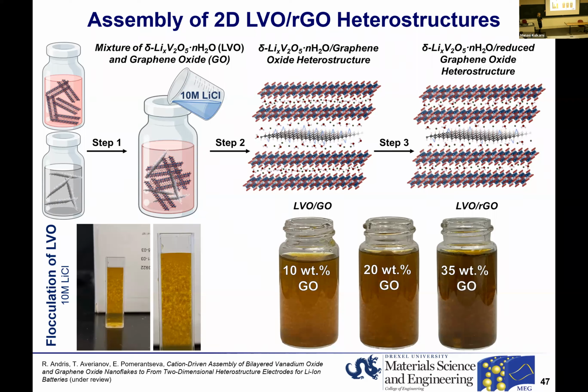So again, by introducing this positive charge from lithium ions, it results in agglomeration of the bilayered vanadium oxide nanoflakes, and that leads to the formation of these agglomerates, and then they can be filtered and form a freestanding film. And this is how these suspensions look when we use different amounts of graphene oxide to make these